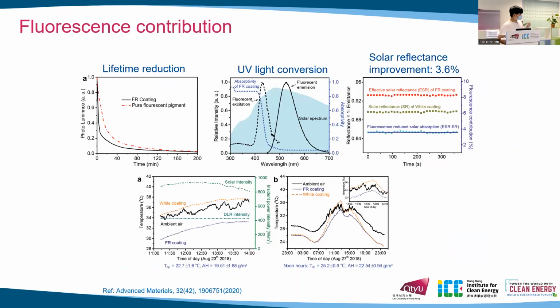And in this work, we want to emphasize that the fluorescence contribution is very important to the cooling effect, because we find that if we add the fluorescent pigment into the TiO2-based white coating, its PL lifetime is significantly reduced. Moreover, the excitation spectrum overlaps with the TiO2 UV absorption, and these two features make the fluorescent coating have a higher solar reflectance. The solar reflectance improvement achieves 3.6% compared to the white coating without phosphor. So we can see the cooling effect. For the FR coating, it can achieve subambient cooling, while for the white coating without phosphor, the temperature is always higher than the ambient air.